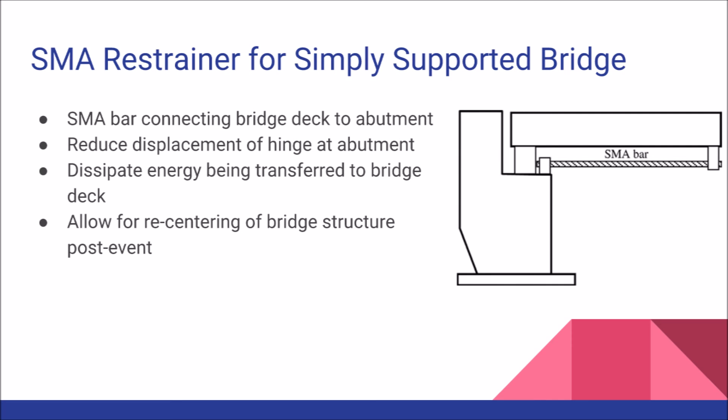Next is the restrainer for simply supported bridges. Both super-elastic and martensite SMAs can be used as damper elements for bridges. The figure represents testing on a full-scale super-elastic SMA bar used for seismic retrofit of simply supported bridges and simulations on multi-span simply supported bridges. The SMA restrainer more effectively reduced relative hinge displacement at the abutment and provided a large elastic deformation range compared with conventional steel restrainer cables. In addition, the SMA restrainer extremely limits the response of a bridge deck to near-field ground motion.